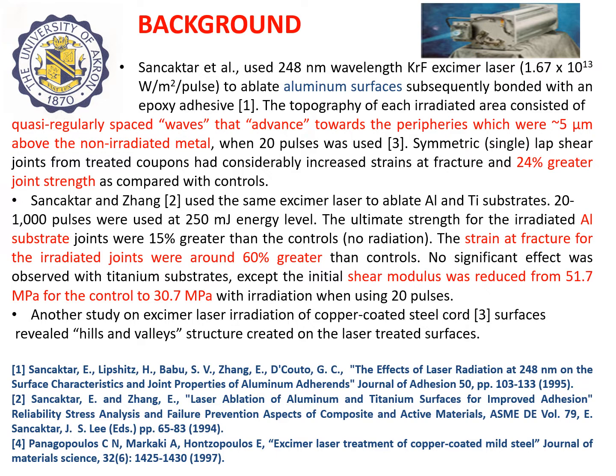We used 248 nanometer wavelength krypton fluoride excimer laser in the past to ablate aluminum surfaces, which were subsequently bonded with an epoxy adhesive. The topography of each irradiated area consists of quasi-regularly spaced waves that advance towards the peripheries, which were about 5 micron above the non-irradiated metal. And this was obtained when we used 20 pulses. We then made symmetric single-lap shear joints from treated coupons and observed considerably increased strains at fracture and about 24% greater joint strength as compared with controls.